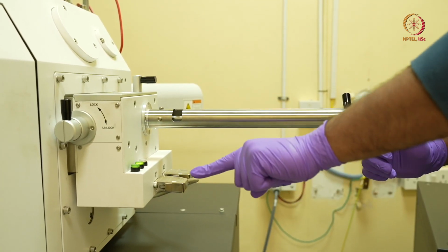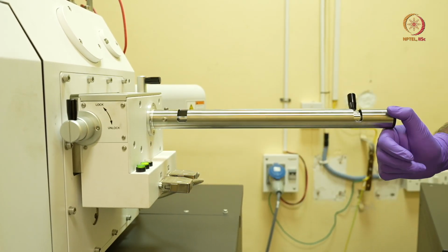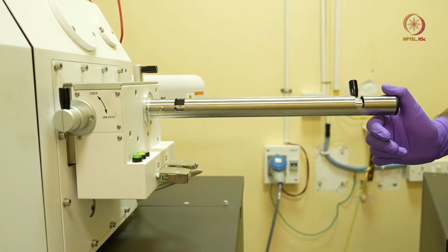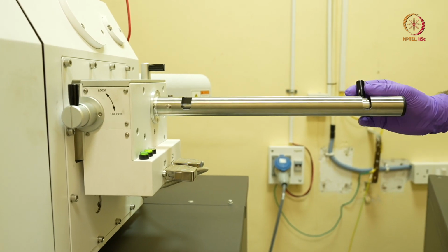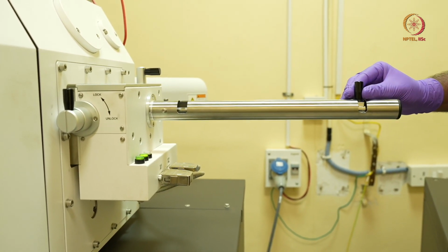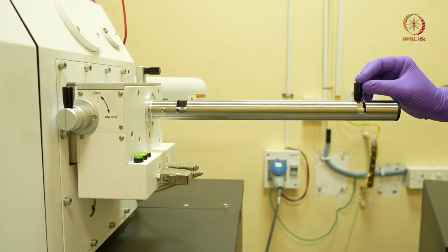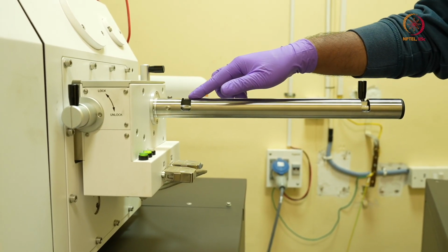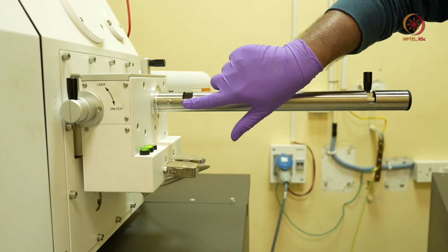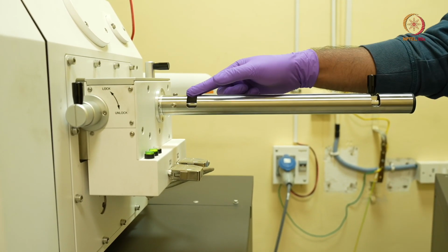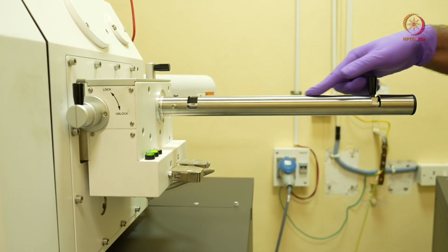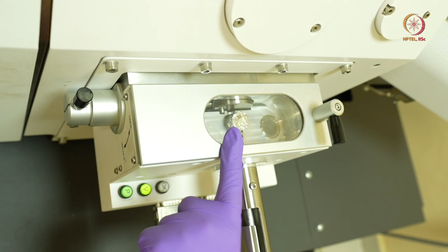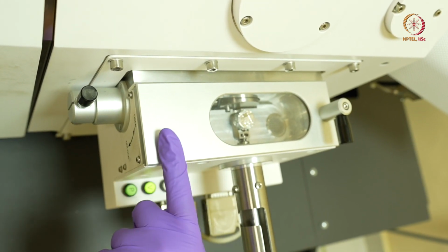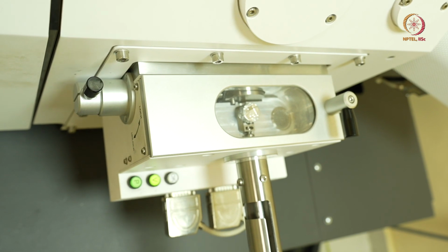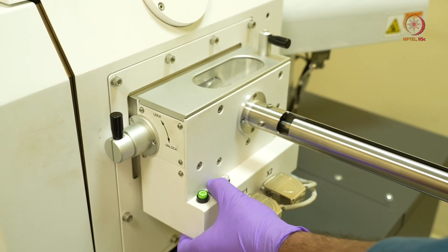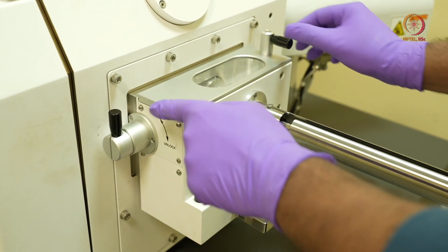You have to press the same pump button. That pump button actually vents my chamber. So it will take at least 30 seconds to 1 minute to vent the chamber. Once the chamber is vented, we use this rod, the quick loader rod, to go towards this stage, turn to the left and move forward, and again we have to turn right to lock the sample, and it will come back. So now my sample actually comes back from the microscope chamber to this small venting box, the quick loader chamber. Now I press the venting button to vent this chamber, open the lid,